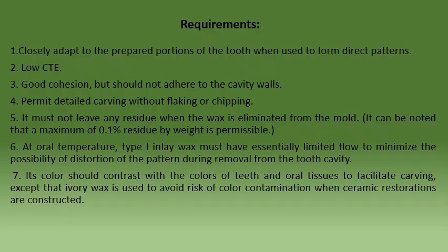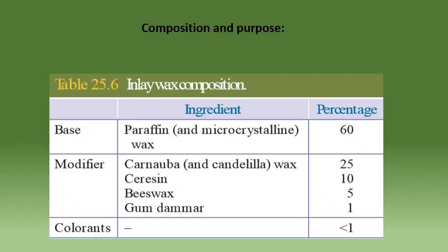One important Viva question that they can ask is, what is the CTE value for inlay wax? CTE is nothing but your coefficient of thermal expansion. Always remember, your inlay wax has got the maximum CTE value, that is 350 into 10 to the power of minus 6 per degree Celsius. This is a very, very important Viva question. Okay, and the composition, everything is the same.